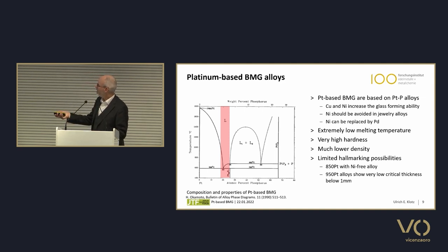Now, this is in atomic percent, 20 to 25 or 18 to 25 atomic percent. And because phosphorus is much lighter than platinum, it's only about 2 to 5 or 6 mass percent that we are needing. There are two alloys that are studied better, and this is one alloy with 850 platinum, but it's nickel-free. That's important, and there is a 950 platinum alloy, but this shows a very low critical thickness.